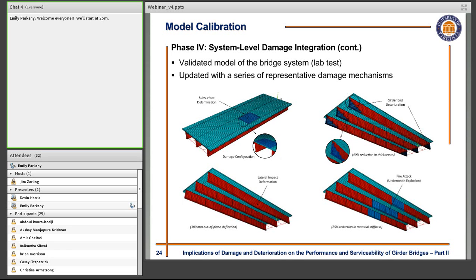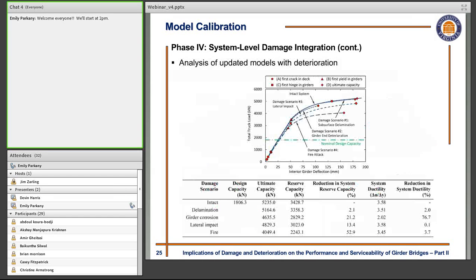So under the same loading and boundary condition, we analyze all of these damage integrated models, and we monitor the same type of response, load versus deflection at midspan of the structure, and we compare this response to the intact system. As you can see, in all cases of damage, we have reduction in the overall capacity of the system as a result of the integrated damage mechanism.